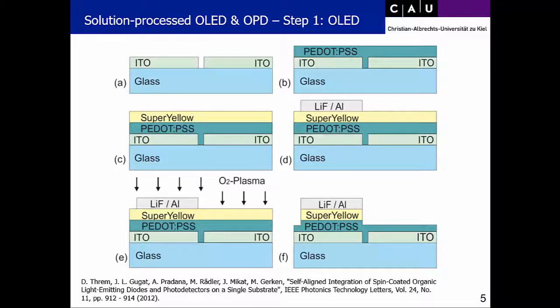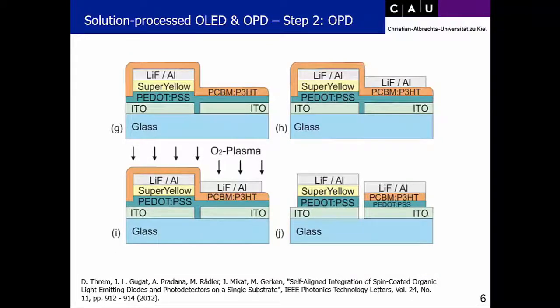So if we apply an oxygen plasma, we can etch away all of the super yellow, and we may have remaining the super yellow under the metal electrode here. So that way we could structure the spin-coated layers. And then in the next step, you can actually see on purpose here, we left some of the PEDOT:PSS as a layer for the organic photodetector.